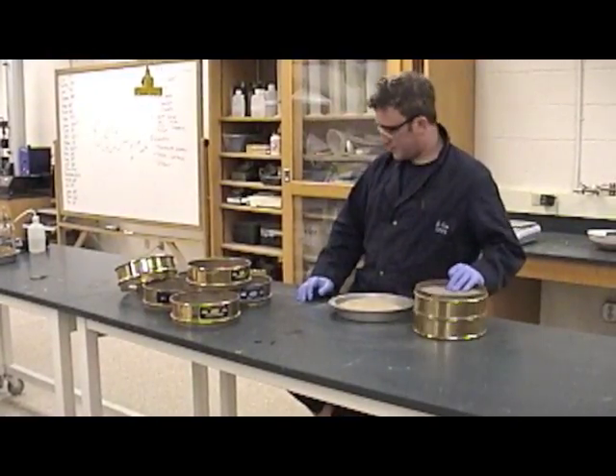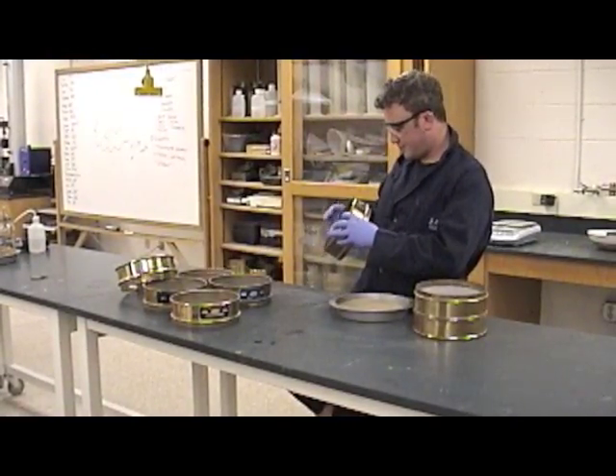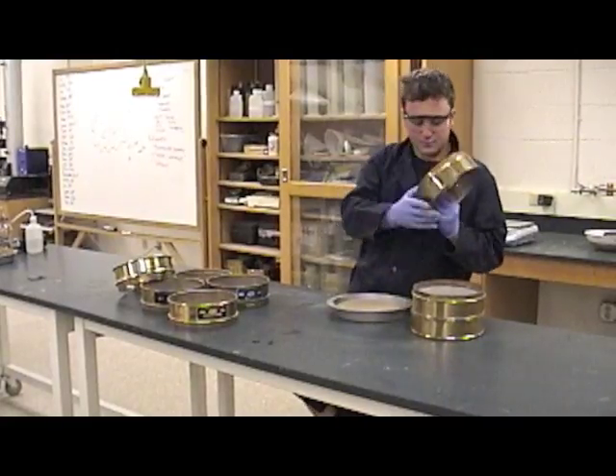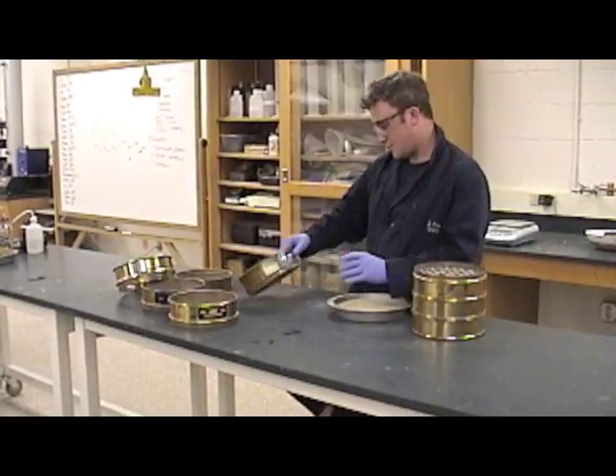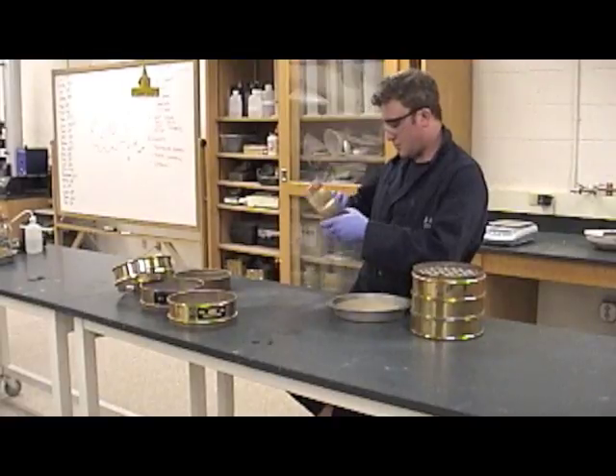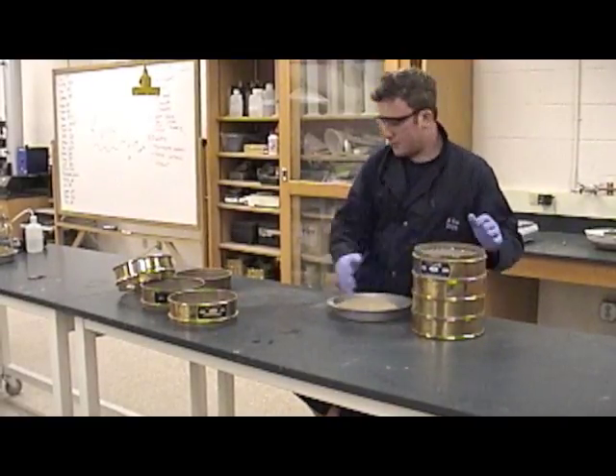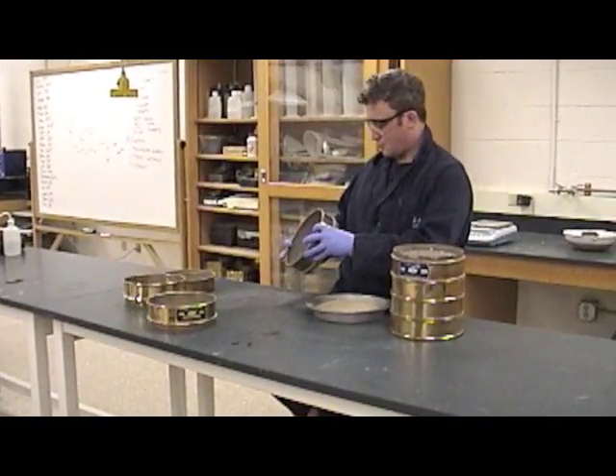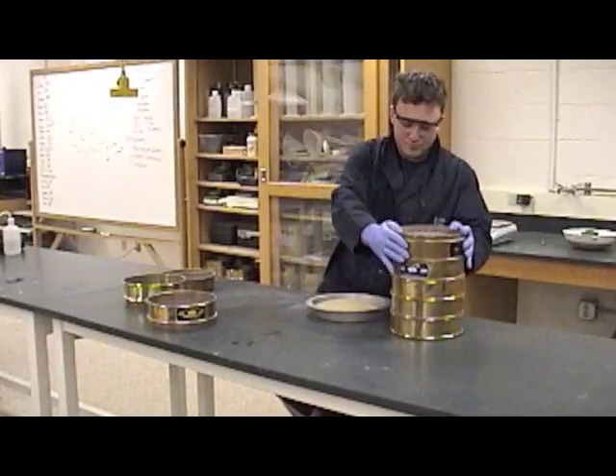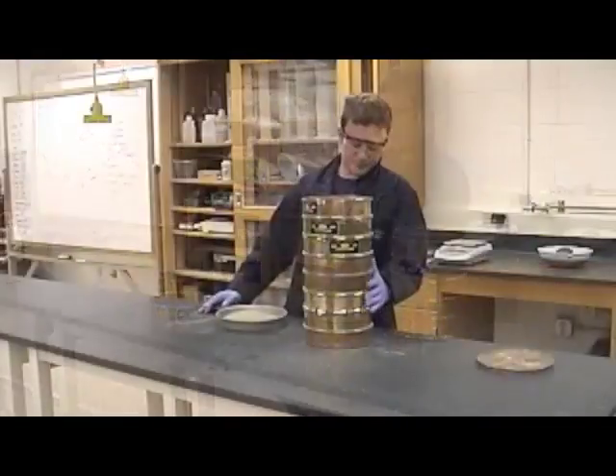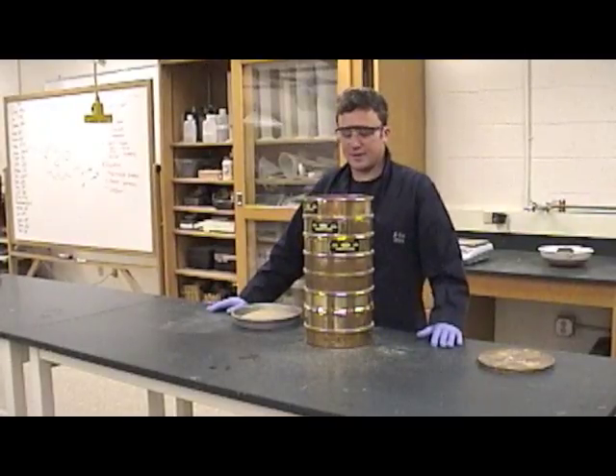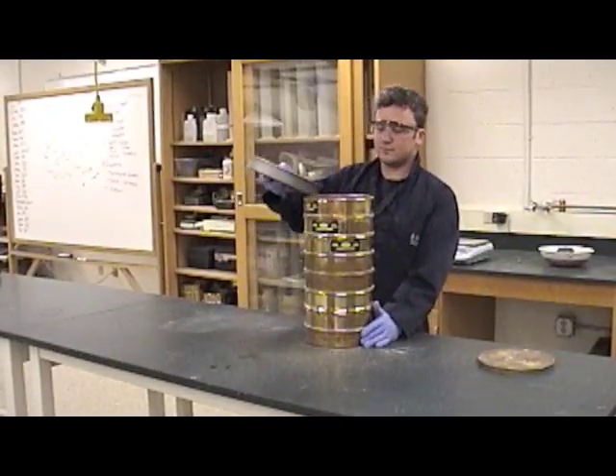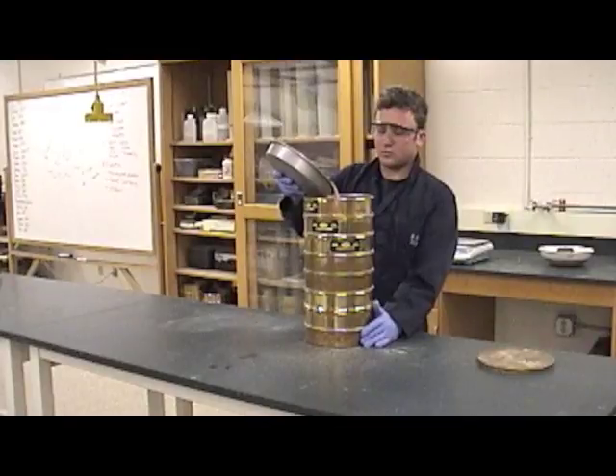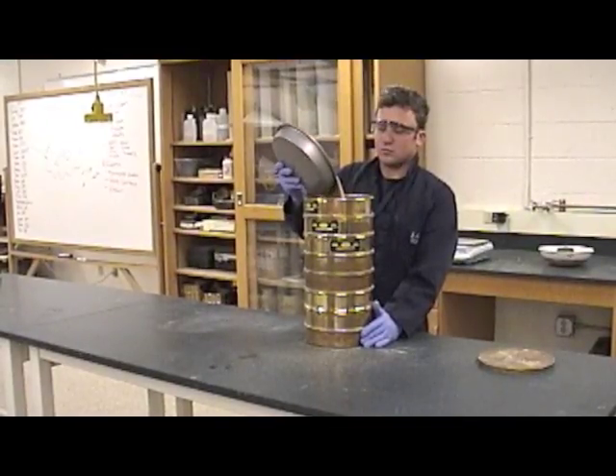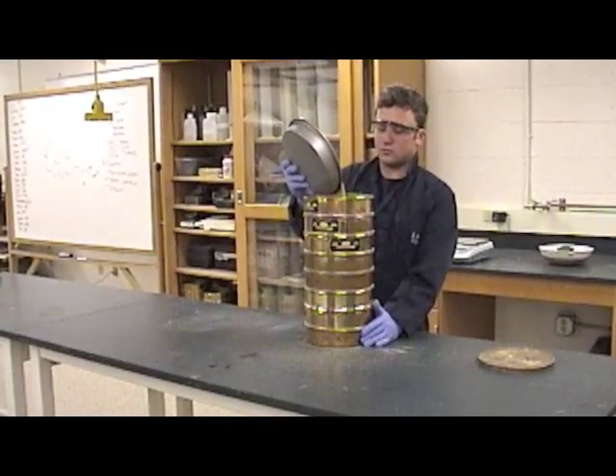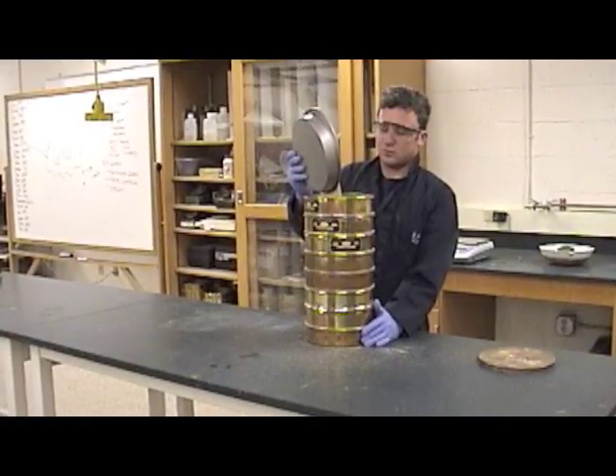Next, we want to nest the appropriate sieves in decreasing sizes. The sieves that we use will depend upon the maximum size aggregate. Here we are using 8-inch sieves with a maximum size of 9.5 mm, as we are doing a fine aggregate sample. Next, we want to pour our sample into the top sieve. We want to take care not to overload any individual sieve. We can use guard sieves if necessary, or test the sample in smaller increments.